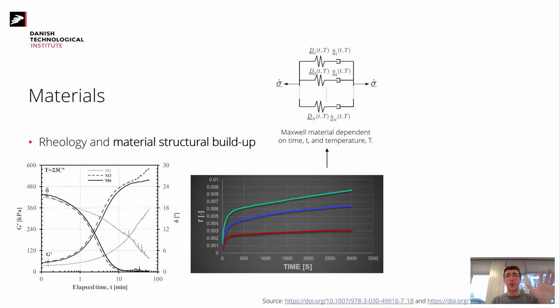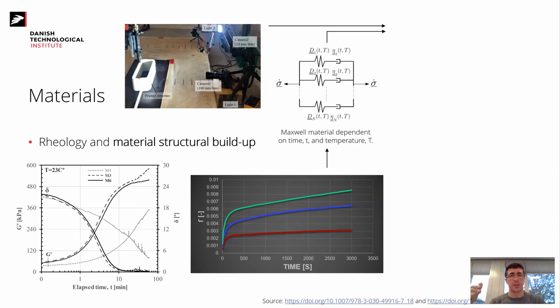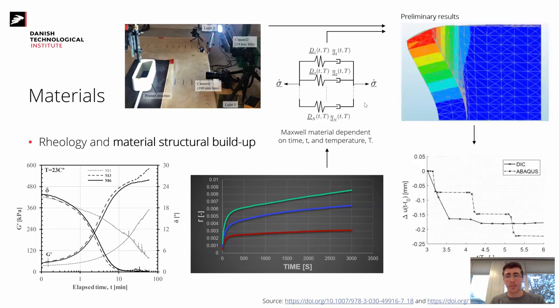And then similarly to this fluid part, on the solid part, we do experimental tests where we are monitoring the deformation using high resolution cameras to run digital image correlation tests. And these digital image correlation tests allow us to map the deformation of a layer during the printing process. So this information is then used to create a finite element model. And then we use the experimental information from the test with the finite element model to see, hey, is our model compliant? I mean, is it describing the phenomenon we observe in the laboratory? Yes or no? Once this is all validated, now we have both a model describing the fluid characteristics of the material and a model describing the elastic characteristics of the material.